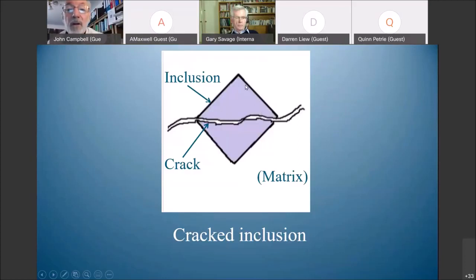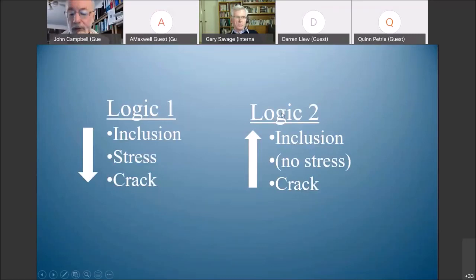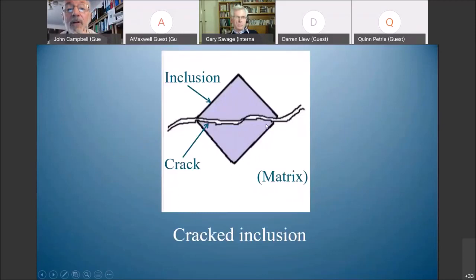So when I ask any normal metallurgist, or I can ask you all, what's the logic here? What occurred first? And you would say, well, the sensible way to interpret this will be, here is our inclusion. The inclusion sits probably in the grain boundary, and then the grain boundary is stressed and the inclusion's brittle. So the inclusion is brittle and the inclusion cracks. So the logic is we start with the inclusion, we provide stress, and finally the inclusion cracks. It's a 1, 2, 3. Now it's interesting. I'm going to tell you now, that's completely wrong.